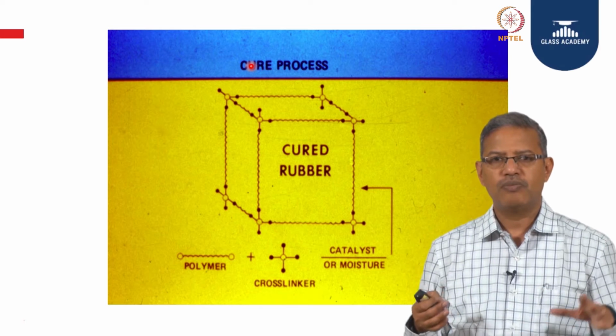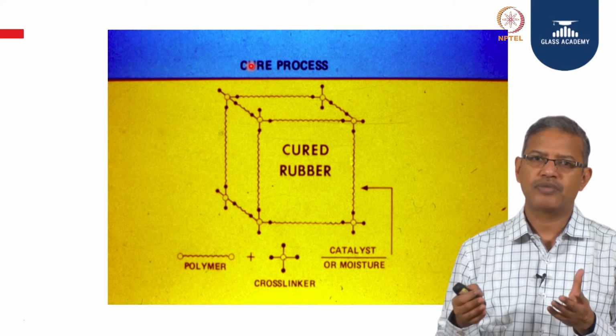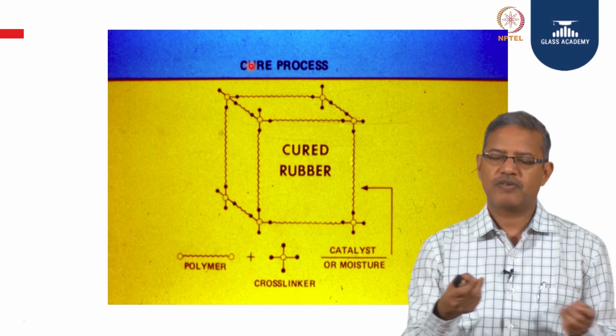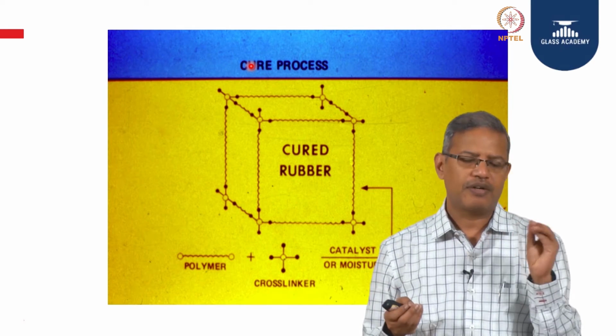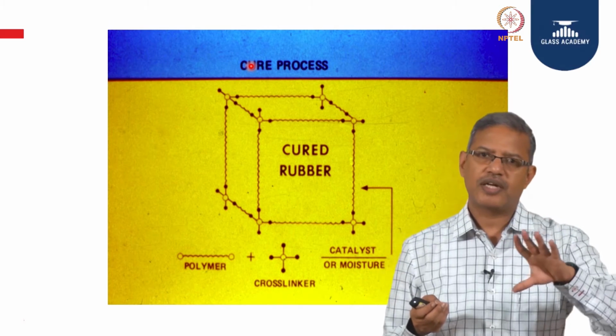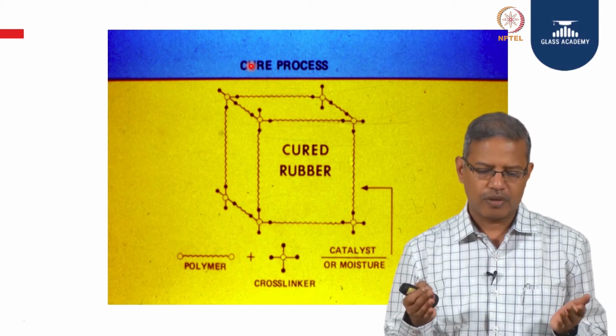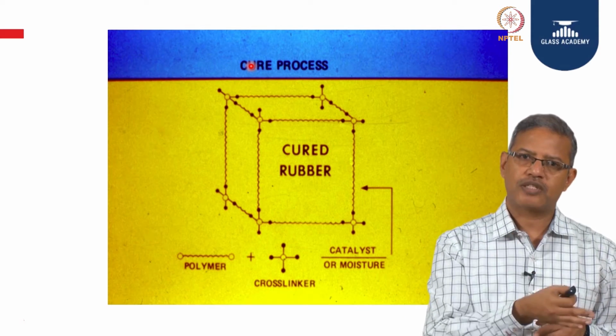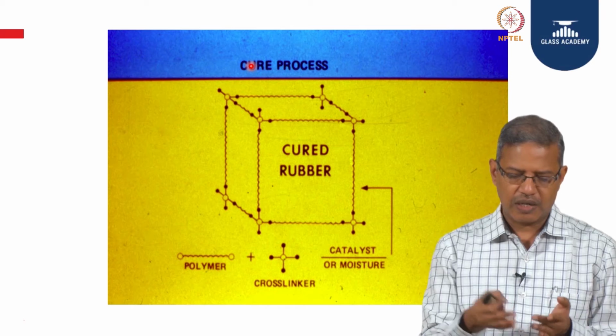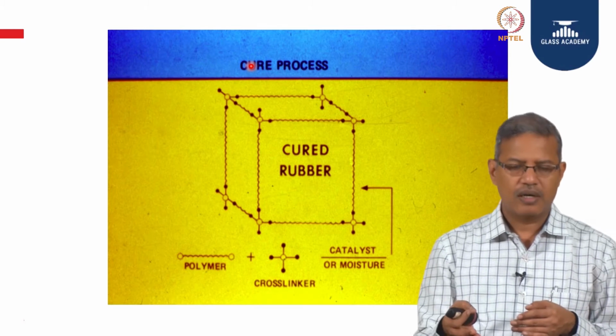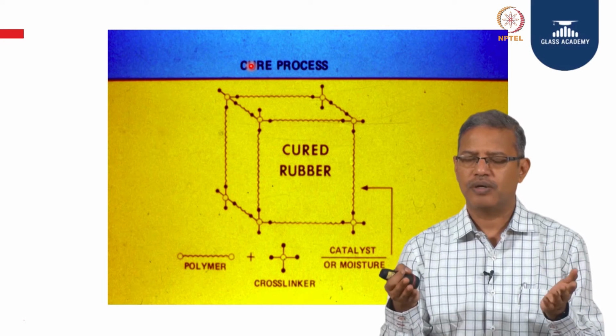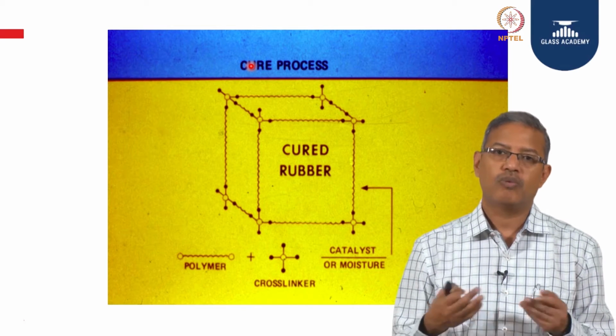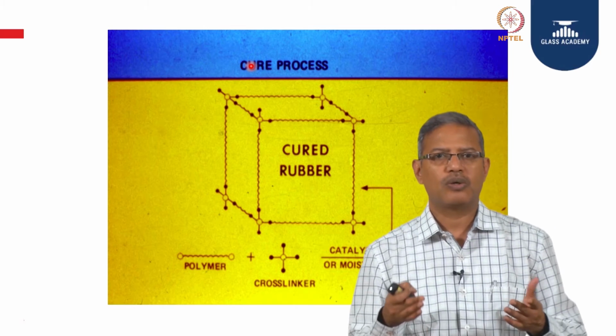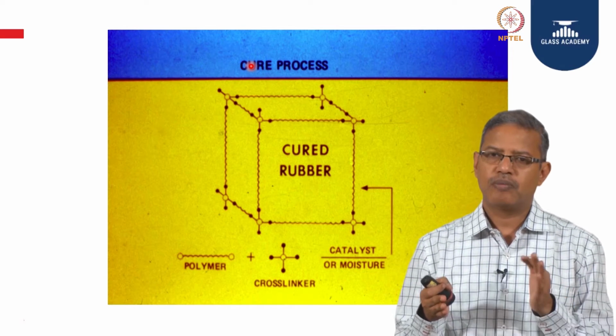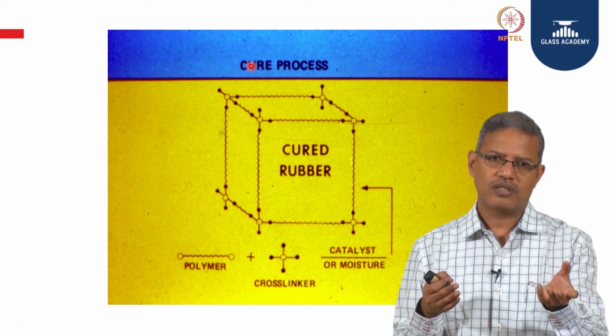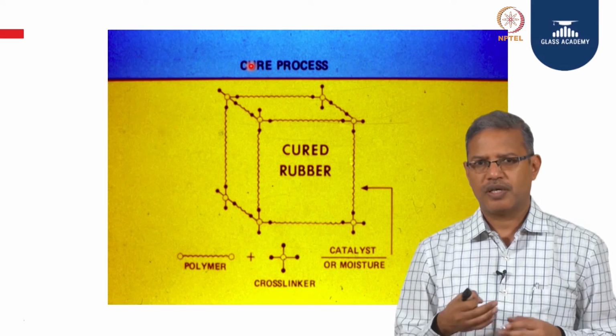When you make the sealant and you apply it, it comes in the form of a paste. This paste, when it is applied, can flow into any shapes, it can fill into narrow depths, and then it will bond and form a rubber. The process of curing from the paste form to rubber is called the cure process, and the essential curing agent for most of the sealants used for our application is moisture. So, it is a moisture cure system. These are called room temperature vulcanizing rubbers. The moisture reacts with the sealant and then it cures. That is the way it works for the one part.